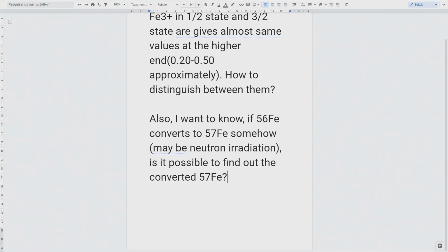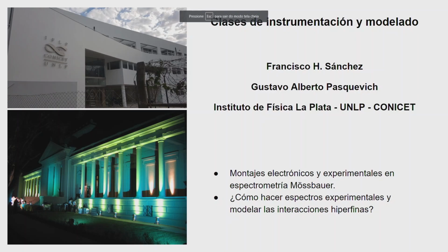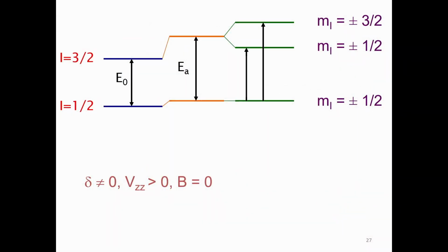Professor, I do understand the theory behind, but I'm pretty sure they have already done it. For example, they build a sample with almost 100% iron, take the Mossbauer spectra, and then they dope a little bit with, I don't know, cobalt. And they keep increasing the doping in the sample. So finally, your question is: you start with some matrix with iron essentially, and after you go to a sample whose composition is iron 100 minus x, cobalt x. So if you consider your matrix, at the beginning, iron is perfectly surrounded by iron.